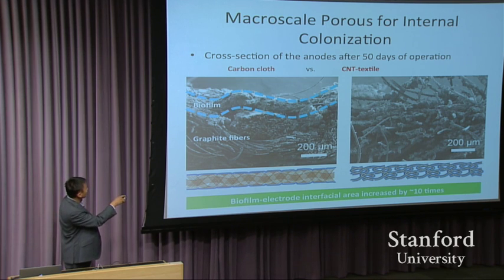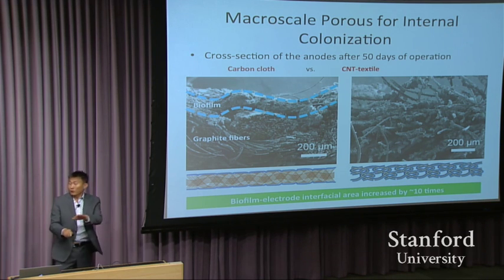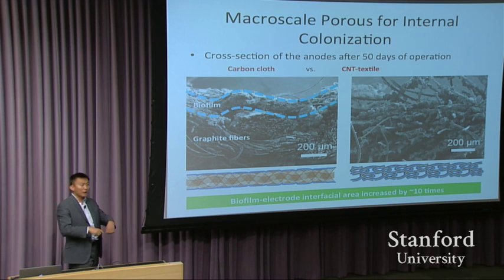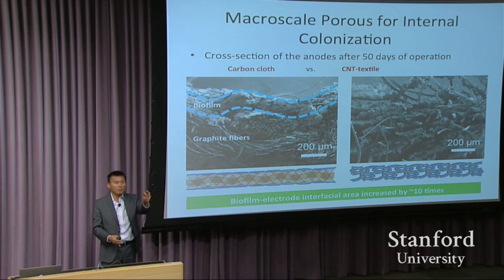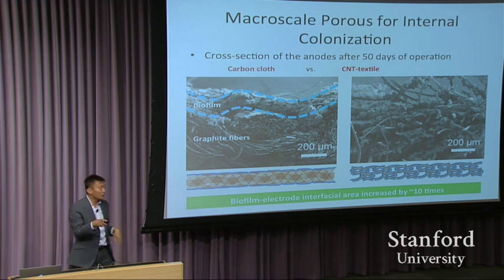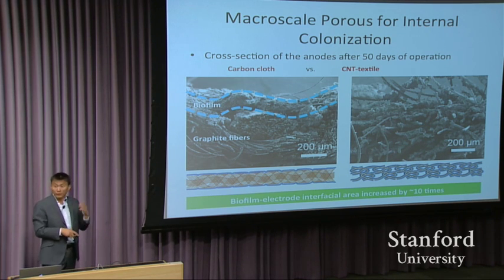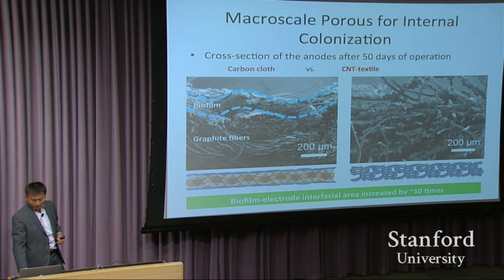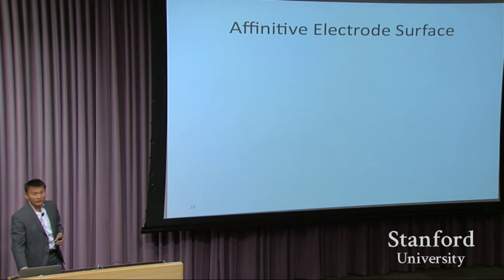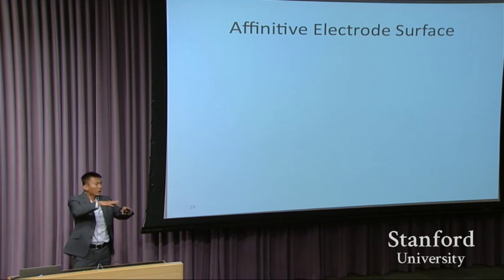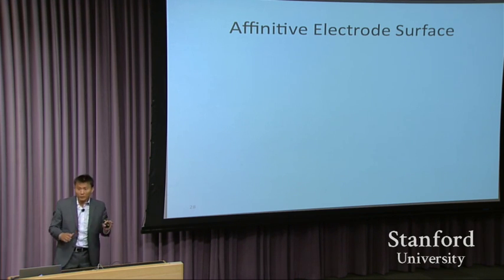This is really just the bottom part of the biofilm. When it's closer to this conducting carbon fiber, then you can have direct electron transfer. You can also have some redox mediator diffuse. There's a diffusion distance. If it's too far away, it's not efficient to collect the electricity. So in comparison, you would expect the right-hand side to be much, much better. So let's look at the affinity, the contact. This carbon nanotube coating is actually rough. A rough surface is something the microbes will really like. A flat surface is like there's nothing to grab on to, so the microbe's attachment won't be strong.